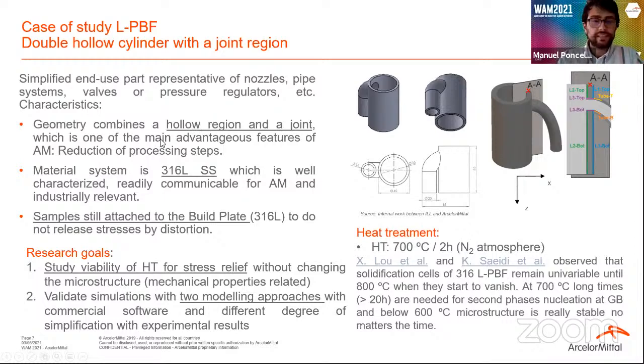We selected stainless steel 316L because it's a very well-known steel in additive manufacturing, very relevant for industry, and also a very easy steel to work with in additive, with a very stable phase. And samples were measured still attached to the build plate, because we wanted to guarantee the stress state that is produced during the process. So if we remove the sample from the build plate, we would be releasing these stresses by distortion, and we wanted to measure the real residual stresses that came from the process.